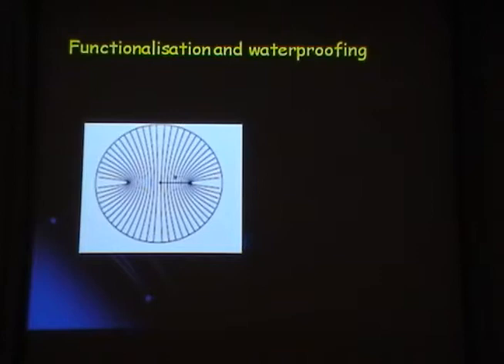I think my slides are a little bit out of order. So let me just change gears so I can follow my slides. One thing is to be able to measure the torque. And then the other thing is to have it applied to something. So if you want to apply these crystals to, say, biological applications, you have to put them in a buffer solution. So when you all of a sudden put them in the buffer solution, they melt. So they are not much use. So what you have to do is put something around them so that you can close the crystal inside and put a shell around it,